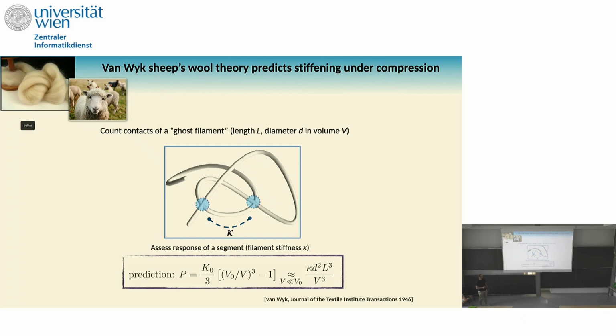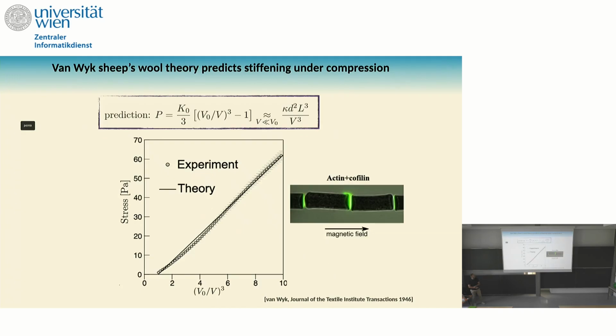If I have 2 contacts that form, when I compress it, I have an energetic cost due to the bending of the filament. Within this ingredient, what you find is that the stress goes with 1 over the volume to the power of 3. Very simple mean field model, just counting the contacts in a ghost filament. If you do that, this is what you find in your experiment, but also the theory works very well and falls on the experiment.